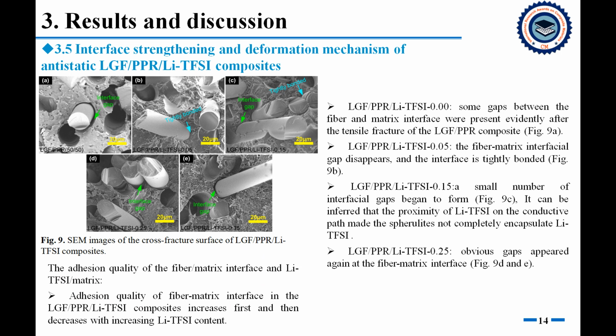The level of mechanical properties is further confirmed from the bonding quality of the fiber-matrix interface and the organic salt and the matrix. The bonding quality of the fiber-matrix interface in the long glass fiber composites increases first and then decreases with increasing organic salt content. Adding 0.05 weight% organic salt, the fiber-matrix interfacial gap disappears, and the interface is tightly bonded.